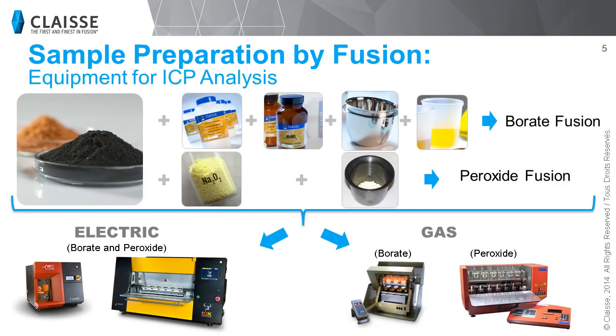The only change regarding equipment when comparing borate solution preparation with sample preparation for XRF is that you change the platinum mold for a Teflon beaker. For peroxide fusion, you need sodium peroxide, which is the most common solvent used for this application, but sodium carbonate can also be used for some applications. The crucibles that are the most frequently used are made of zirconium or nickel. As for the two previous methods, it is possible to use gas or electric fusion instruments. The Neo fusion instrument and the Eagon can be used to prepare peroxide fusion. Also, we offer the peroxide fluxer instrument, which is powered by gas and fully dedicated to peroxide fusion.